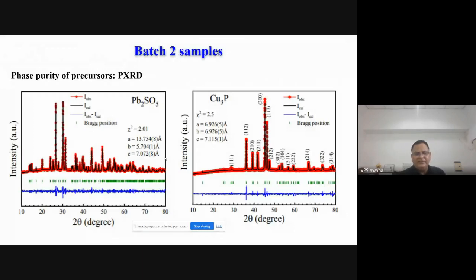Pb2SO5, this time we did the Rietveld analysis of our precursors for the first time, because I was very hopeful that this compound can be superconducting. The reason was this: the hexagonal of Pb, which was running through chains in the middle of the structure, if the lead can be changed by copper over there, a shrinkage of around 0.5% can in fact create enormous pressure in the unit cell, and that can give rise to superconductivity.